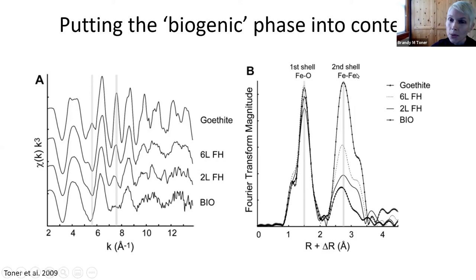And there's three distinct iron-iron interatomic distances in that second shell. To be able to model all three of those interatomic distances, you have to have pretty good data out to a K of 14. I mean, depends on your perspective. It's quite hard for us to get really great data out to a K of 14. But you want to be out in that range so that you have enough spectral resolution to model the three iron-iron interatomic distances in the second shell. And when we did that,